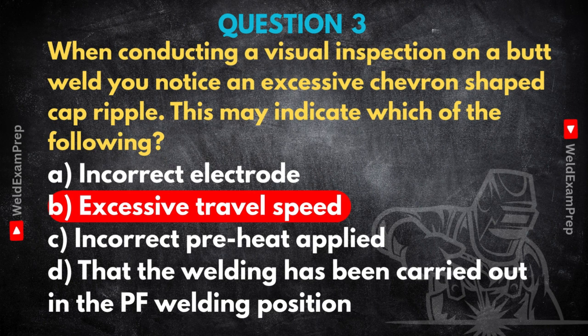And this isn't just cosmetic. It often indicates that other things might be wrong too, like maybe not enough fill or poor fusion at the root because the heat didn't penetrate properly. So it's a surface sign of a potentially deeper issue caused by going too fast. What about the other options? Why aren't they the primary cause of this specific ripple? Good question. Incorrect electrode. That usually shows up as maybe arc instability, excessive spatter, maybe the final weld chemistry is wrong. But it doesn't typically create that specific elongated chevron ripple pattern.